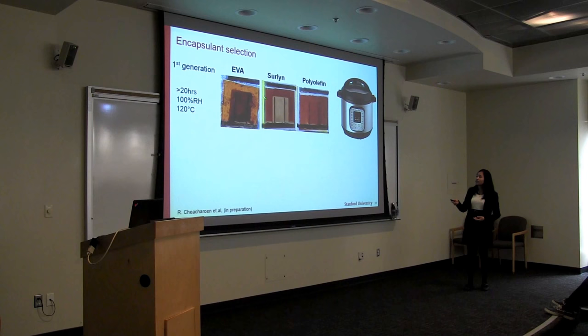We can see a clear degradation due to acetic acid in EVA. In Surlyn, we did not see any reaction between perovskite and the encapsulant, but we do see some delamination here, as I have mentioned earlier, from the temperature cycling, probably because Surlyn is really stiff. Well, for polyolefin, I did not see any delamination, and I did not see any reactions between the encapsulant and the perovskite, so it seems to be the best of these three families.